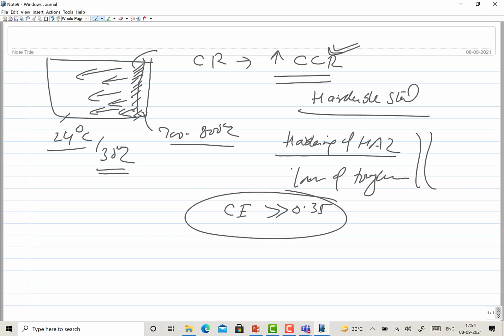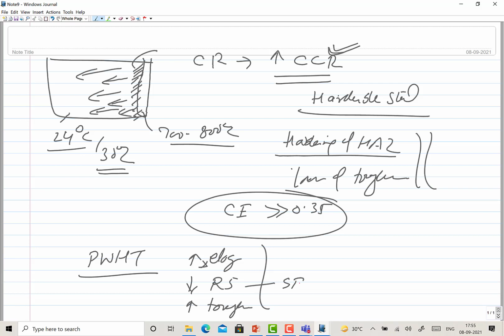There is no fusion zone, so certainly the heat affected zone, including the interface, needs to be corrected or rectified for more favorable properties, and that is why hardenable steel friction welds need to be given post weld heat treatment, so that you can restore the elongation or ductility, you can reduce the residual stresses, so you can say stress relieving, and you can improve the toughness through tempering. Okay, so improving the toughness, these are the different heat treatments only. So you can say stress relieving or